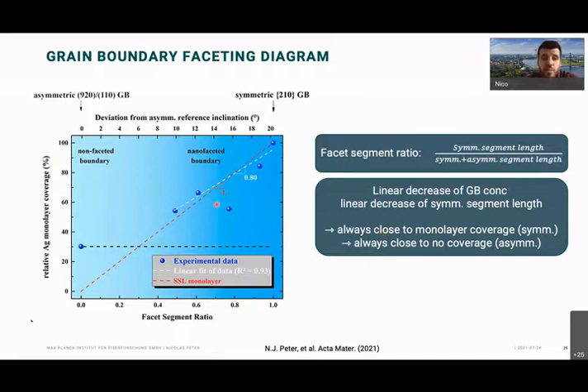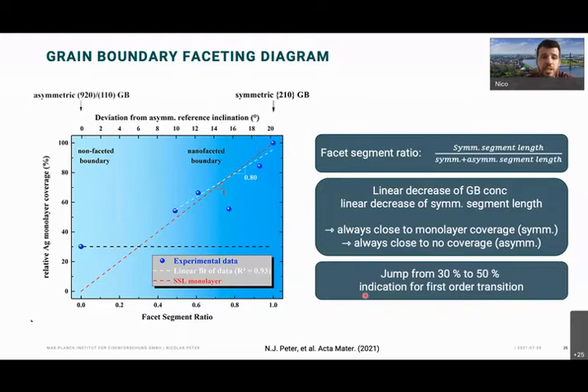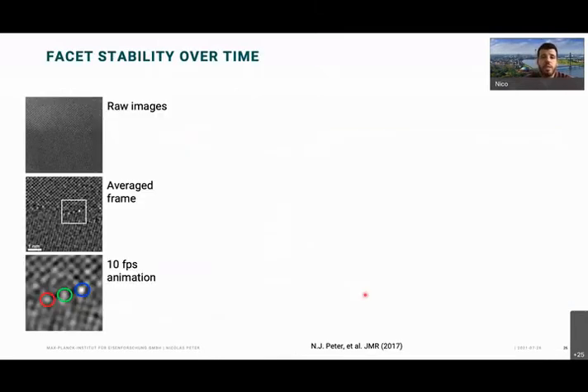And then there's a third portion of this graph that is interesting. At 0, so we have 0 symmetric segment. This is the asymmetric boundary. We see it has 30% silver. So it takes up silver as expected from the simulations also, but much higher than it should be. And then suddenly it jumps to 50% and does a faceting. And this jump here indicates a little bit that this actually is a first order transition that we observe in this case.